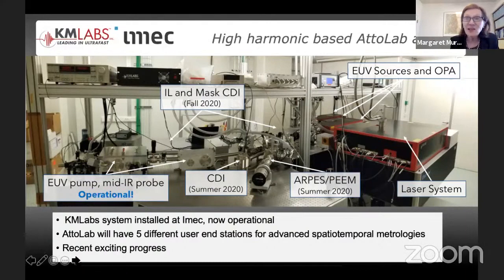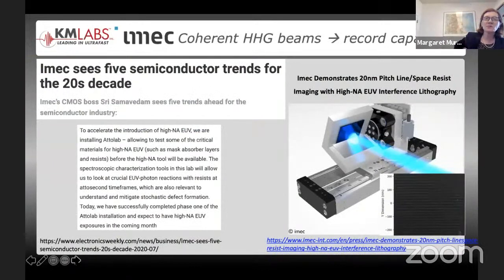And they've gotten off to a very good start. These are just amazing teams. They feature this AttoLab in the advanced R&D they're doing, and they were recently able to use a very simple Lloyd's double mirror to print very nice 20 nanometer full pitch lines. And so this was done with high harmonic generation.